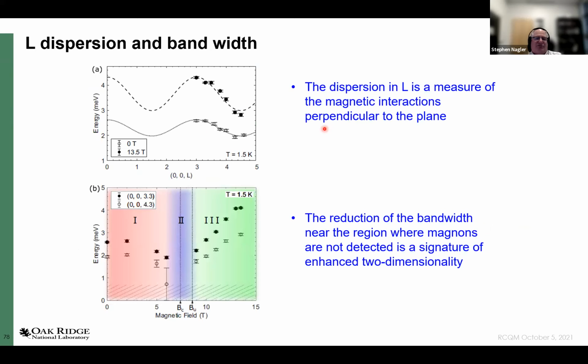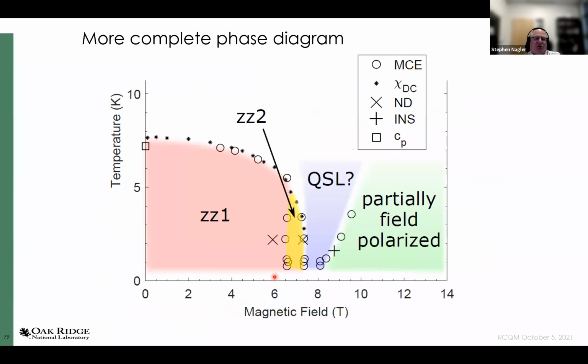Okay, here's the dispersion measured at 13.5 Tesla and 0 Tesla along the L direction. And here are the energies. And in this region here, we're unable to detect what you would call magnon peaks. So this, combined with some magnetocaloric effect, caused us to construct this phase diagram.